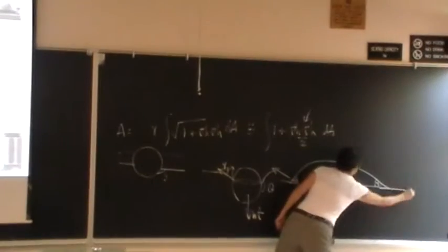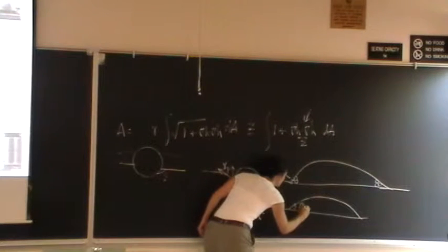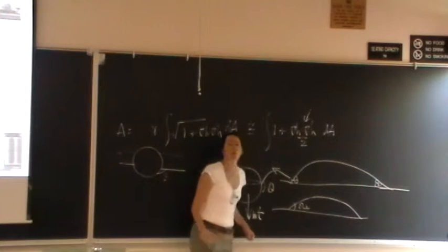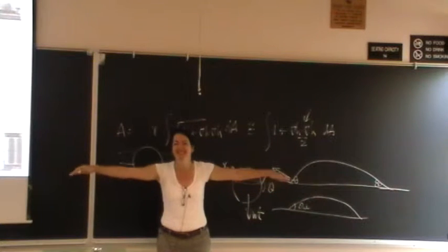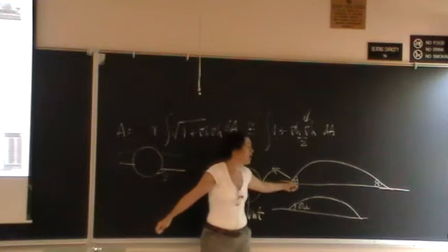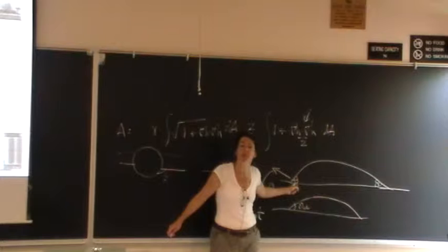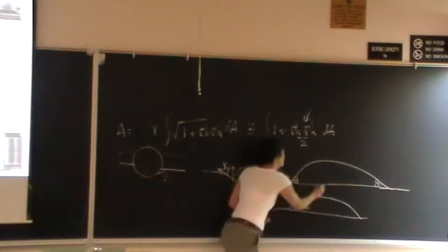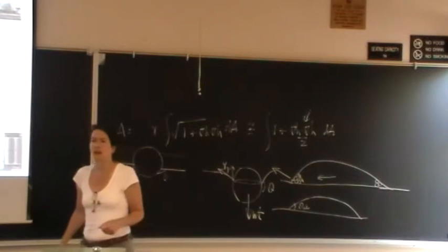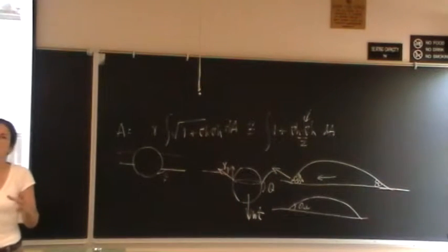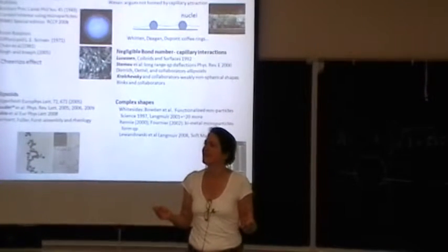The drop is put down with some contact angle, called an advancing contact angle, and it can't move until it reaches a receding contact angle. It gets messy. While it's trapped, colloidal particles get washed to this three-phase contact line. The presence of those particles pins the contact line, so there's a continued outward efflux of particles toward that contact line. At the end, one is left with a ring, and that ring is called a coffee ring.